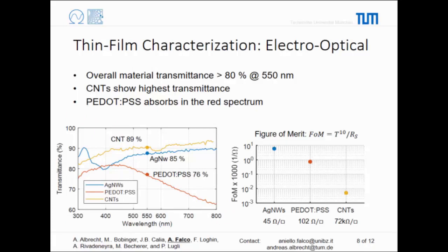For the layer thickness, we used the CNTs, which were the top performer, but the resistance of the CNT layers is also relatively high. This that you see here is another figure of merit that takes into account also this part. So it takes into account the sheet resistance, that for the semiconducting CNTs we used was 72 kilo ohm square. You can really understand from here that if we employ carbon nanotubes, we're gonna have most likely a very high voltage, but we cannot transfer power because the resistance is very high, and so the power transfer will be very low. So this is not perfect for energy harvesting, although it's great for sensing applications.